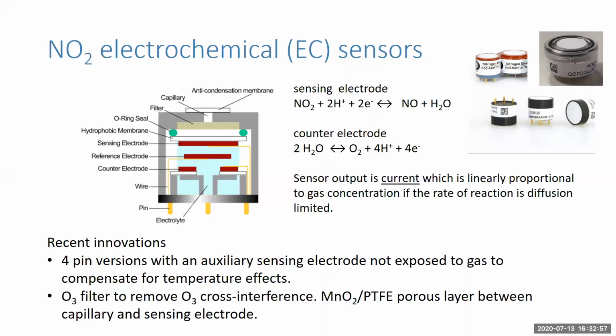And the second significant innovation is the development of ozone filters, which are usually located just between the inlet capillary and the sensing electrode. And this is to remove ozone cross interferences, a well-known interference for NO2 electrochemical sensors. The filters are usually composed of manganese dioxide material coated on a PTFE porous substrate.